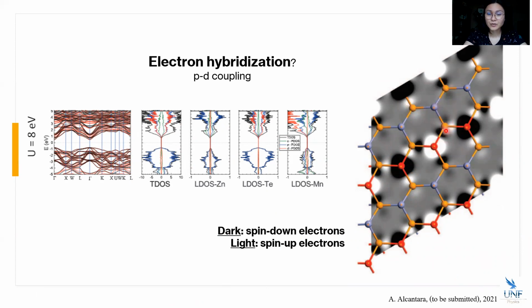But now the tellurium is ignoring the zinc and it's preferring its nearest manganese neighbors through these multi-node interactions. And so you can see that there is a distinct interaction in the spin density, and there's an overall change in interaction through the lattice, suggesting this is how the spin glass state forms.